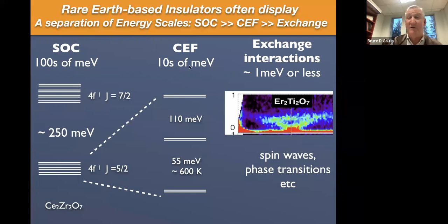But actually, we can understand all of this. And understanding all of this tells you about the nature of whatever the degrees of freedom are. Okay, so as it'll turn out in the cerium 3+, there's a pseudospin 1/2 degree of freedom associated with this low energy doublet that is the crystal field ground state. So there's a pseudospin 1/2 degree of freedom connected with it, and we can understand the wave function of that pseudospin 1/2 degree of freedom. But we can only do that if we do this high energy spectroscopy first. Okay, so that's actually what we'll do.